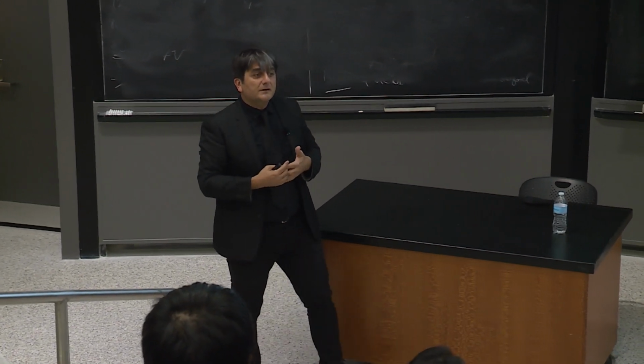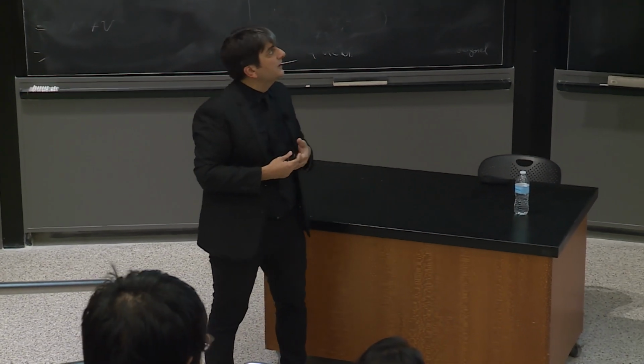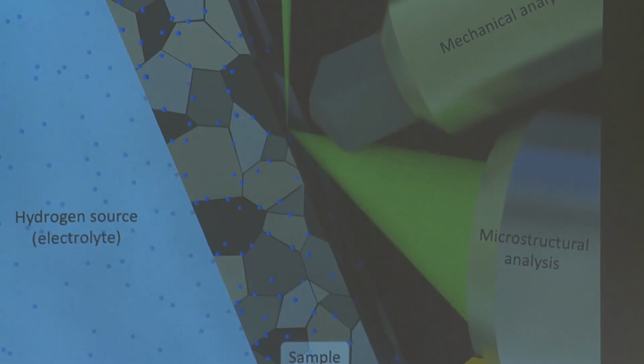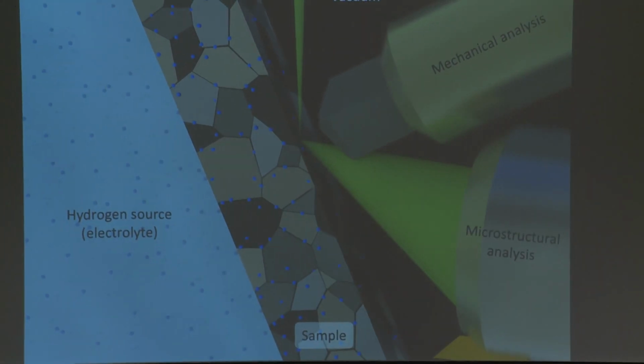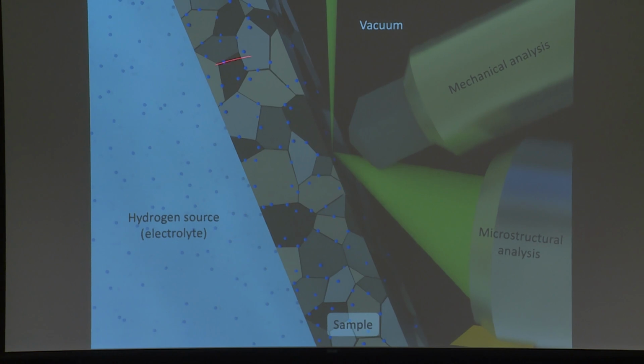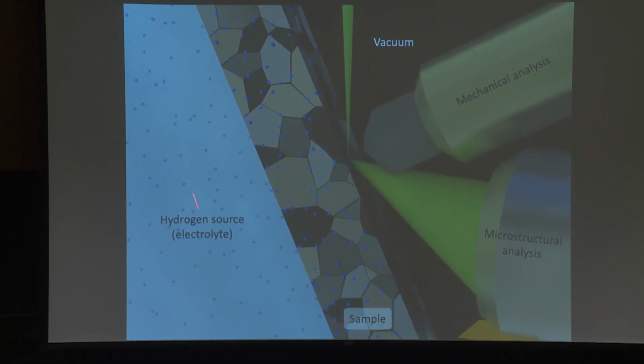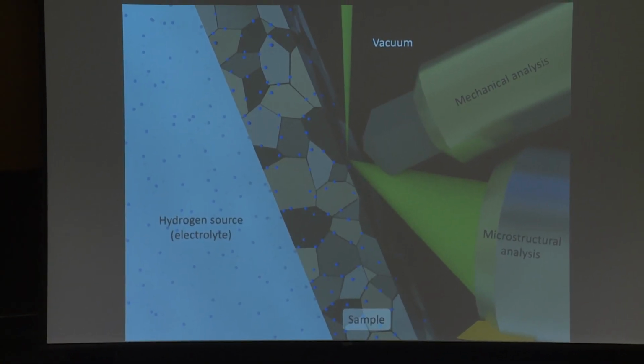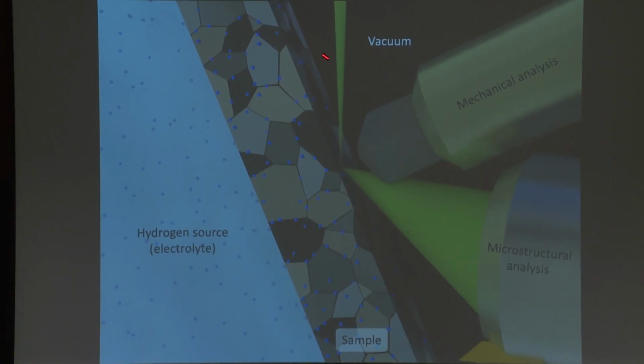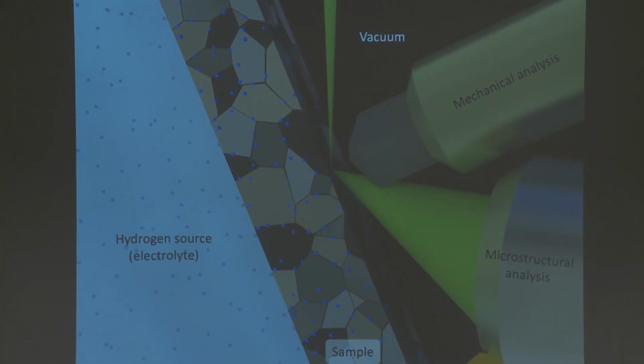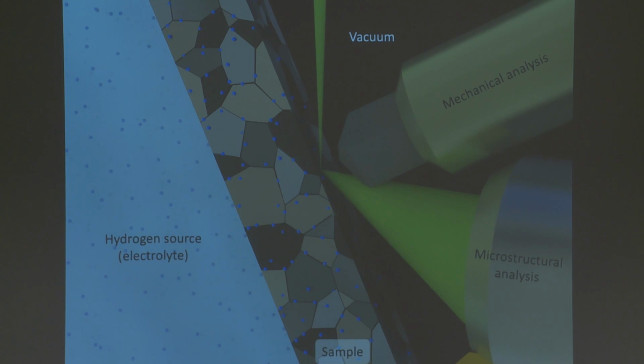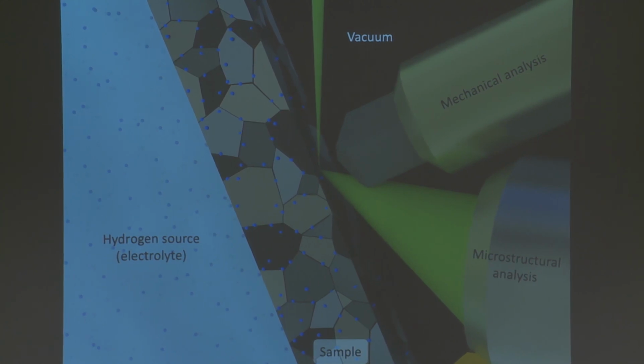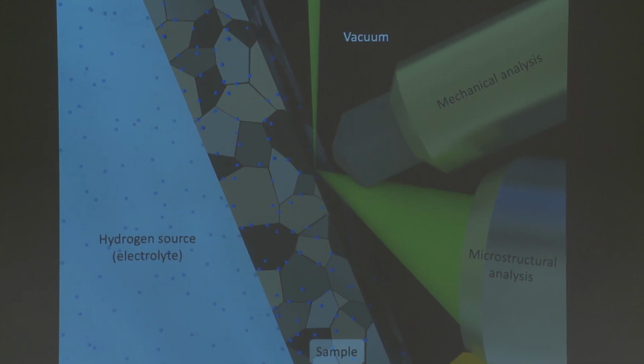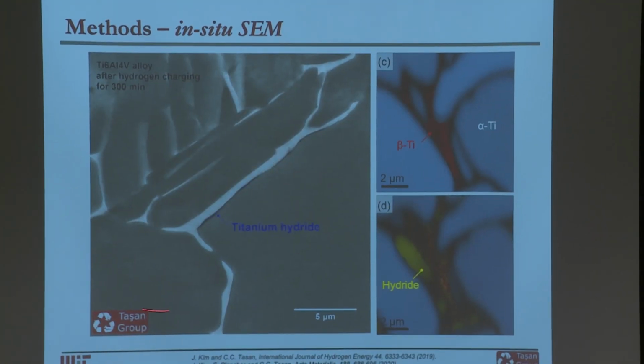Now you can switch to the in situ SEM charging setup. In the in situ SEM hydrogen charging setup, the basic idea is simple: you have in the SEM a little reservoir that contains some hydrogen source, some electrolyte, which is limited by the sample itself. And on the other side, you have your probes. It could be mechanical probes, or it could be your electron beam. So essentially, it's a permeation test where you are charging hydrogen from the bottom, and you are looking at it from the top to understand what's happening. So if you do this, you get movies like this one here.